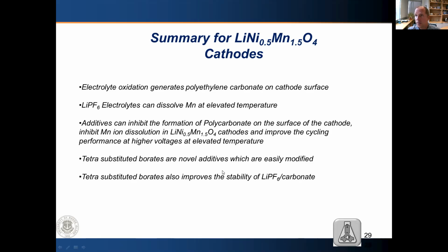We developed a series of tetra-substituted borates as novel electrolyte additives. One of the interesting aspects with these tetra-substituted borates is that we can easily modify the structure of the tetramethyl borate to utilize these borate additives as surface functionalizing species, to tailor the reactions on the surface of the cathode and tailor the functional groups that are delivered to the surface of the cathode. And the tetra-substituted borates improve the stability of the LiPF6 carbonate electrolytes as a bulk material.